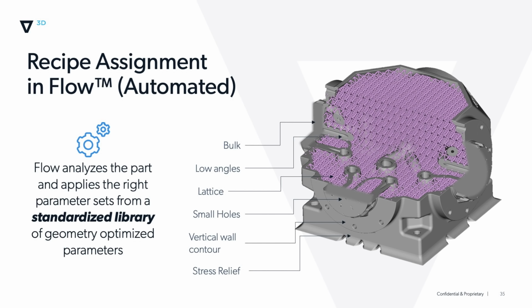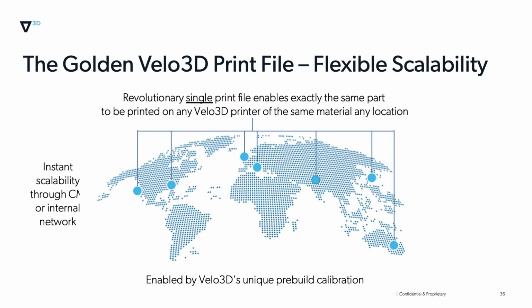One thing I will mention here is the stress relief or stress reduction. We have the ability to print this Ti-6-4 material without the incredible stress risers that exist. We have a way to mitigate the stress inside the printed material, and we aren't as plagued by cracking problems as in other materials or other printers printing the same material. You know, scalability is a big concern, especially when we're printing one part and want to print it a lot of times.